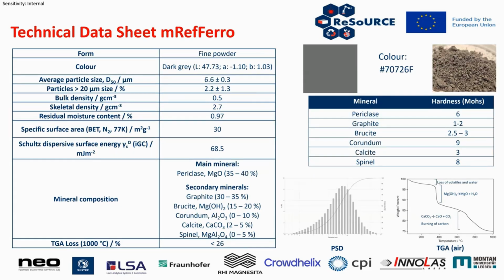We also have the same data for the mRefFerro with similar results, a little bit larger loss in TGA because there is more carbon in the form of graphite in the formulation, which comes off at the higher temperatures. And again, this color is different. It's a darker gray because of that graphite content, but we still need to confirm how reproducible that color is if you're looking at a coating application.